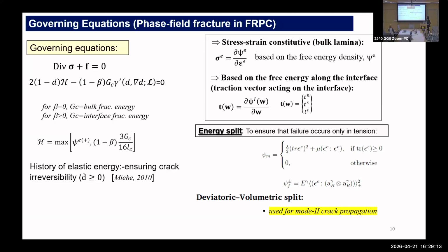So then, of course, H from the construction itself is the maximum of the history of the elastic strain energy and factored by a term which basically acts as a threshold. And just by manipulating the length scale parameter, we can actually craft this model to match the tensile strength of the materials too. Okay, so I'll come back to that detail. But for the time being, once we have the governing differential equation, we have additionally the bulk lamina constitutive, as I just mentioned, a very simple rule of mixture type decomposition to begin with. And then we have a traction separation law to describe the cohesive interface behavior.